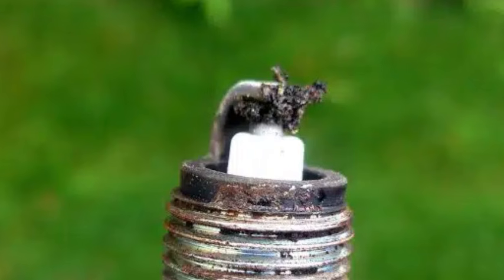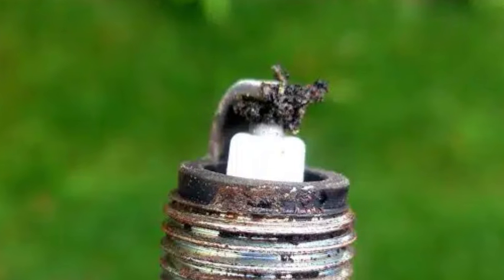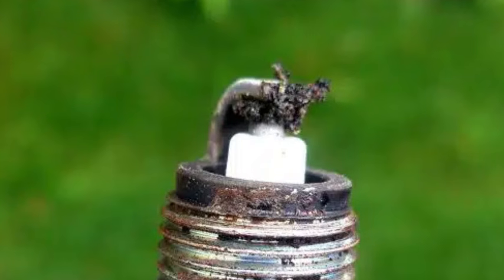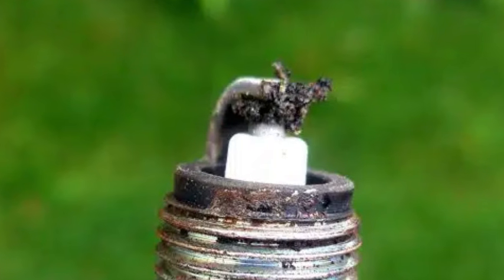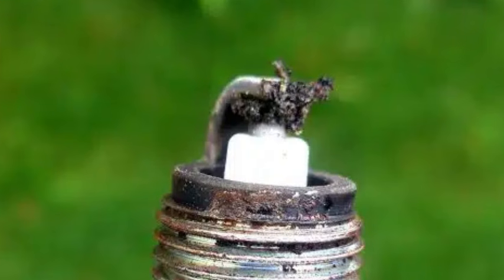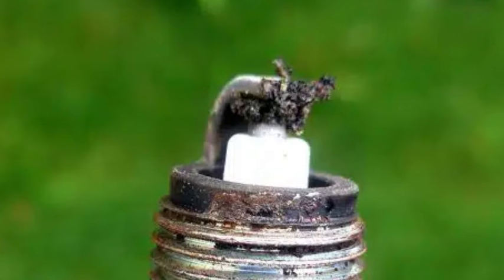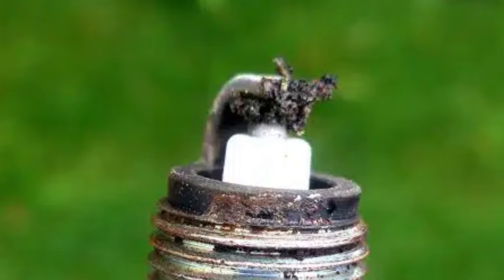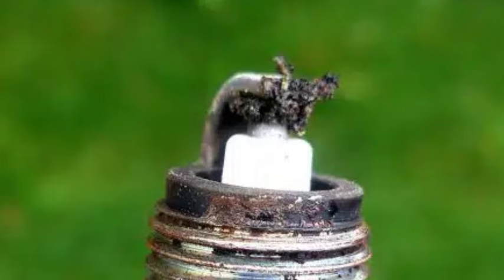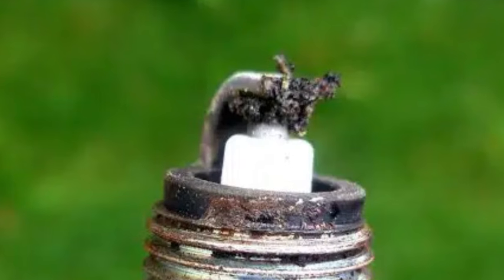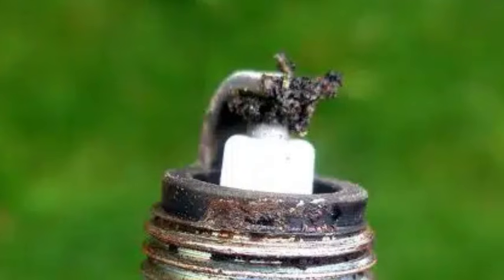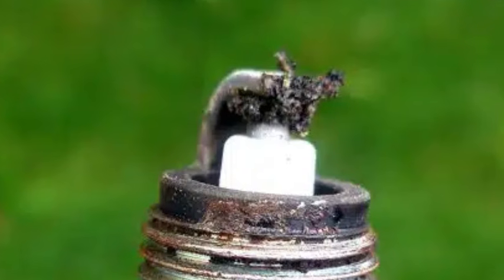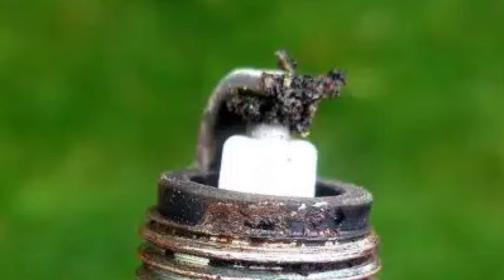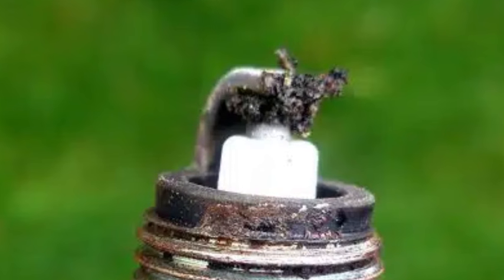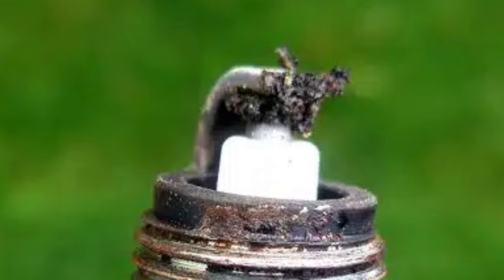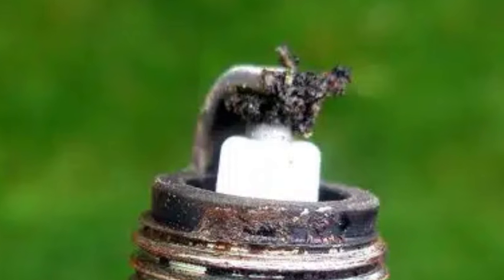The problem arose when the engine ran at low operating temperature with a rich fuel mixture. Under those conditions, the lead did not fully vaporize and pass out through the exhaust. Instead, it condensed and deposited on the relatively cool firing end of the spark plug, building up a hard, electrically conductive crust that eventually bridged the gap between the electrodes, shorting out the spark and stopping the plug from firing. The B-29, with its long cruise segments at high altitude with rich mixtures, and its tendency to run the rear cylinders cool during certain phases of flight, was a lead-fouling machine.